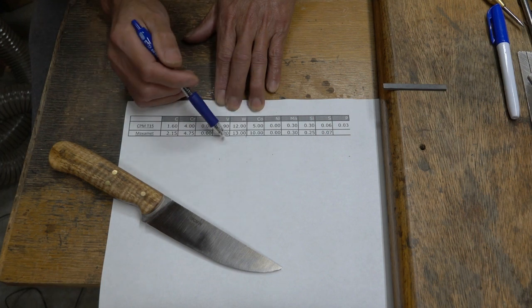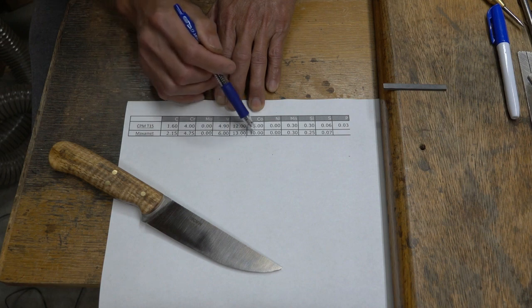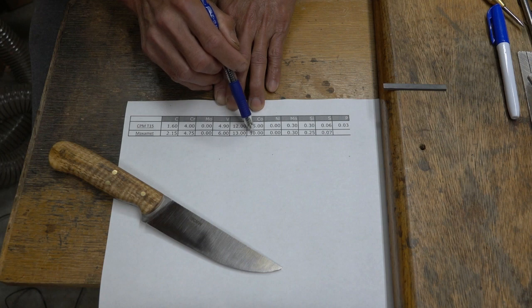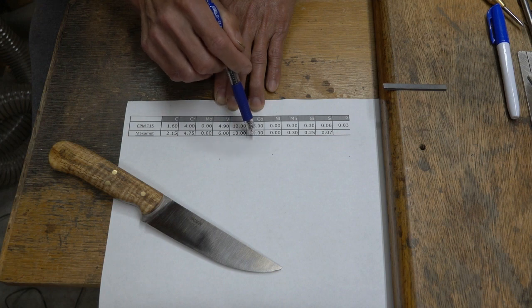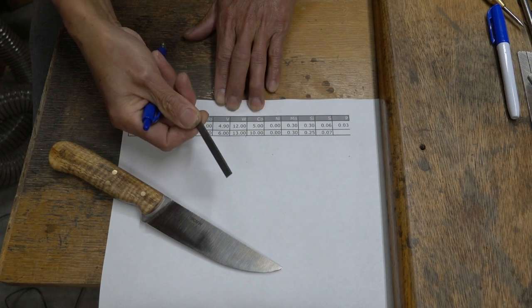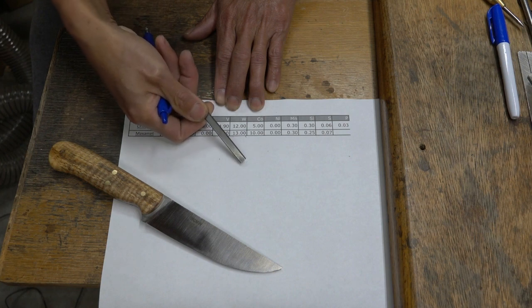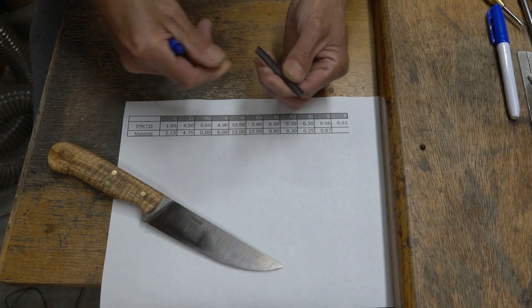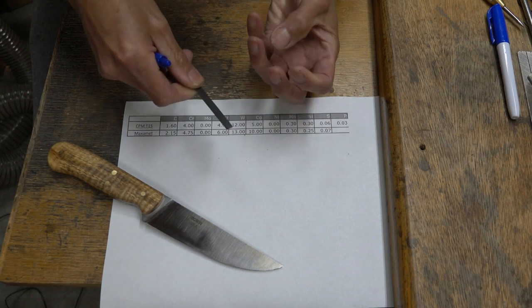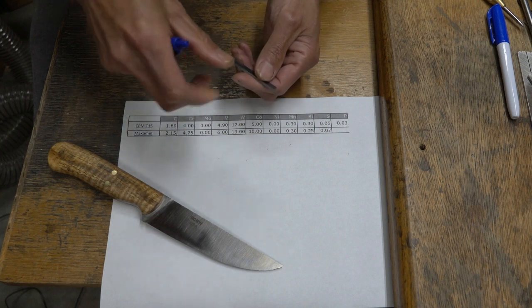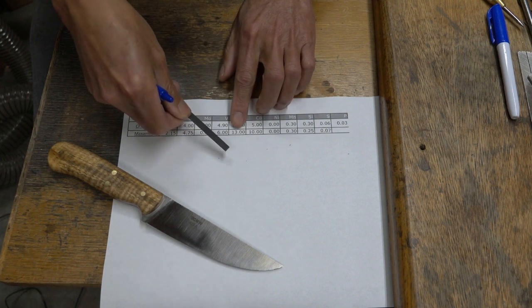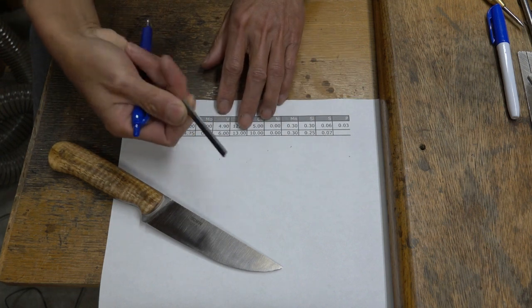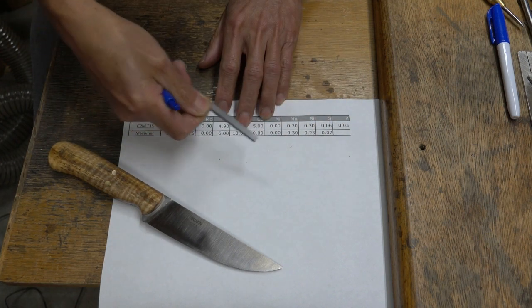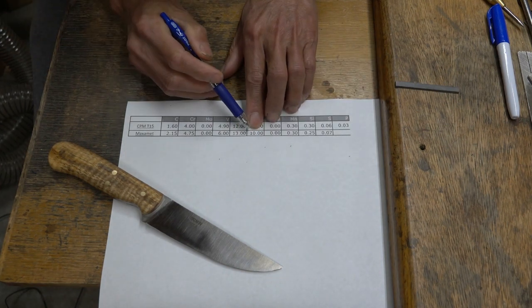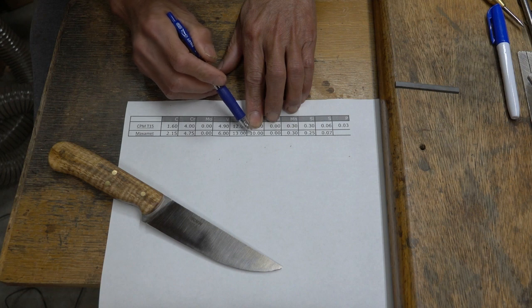And now for Maxamet, look at that and say, okay, because I have a lot more carbide in it, a lot more cobalt. But whether they need 10%, you see, this is pure tungsten here. There are a lot of particles in here. For this one they have fairly fine size tungsten, what they call grain, but actually I'm not going to think of it as a particle. And in this matrix they got 10 to 15%. This is pretty much pure tungsten, right? Except for cobalt. And so why do you need that level? What is all the extra cobalt going to do?